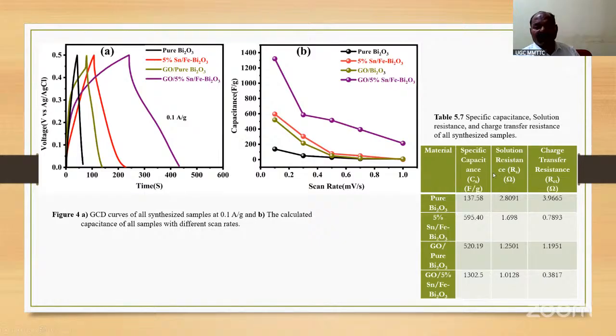For this it is 137.58 farad per gram, and the solution resistance was also calculated. The specific capacitance we got after doping, the addition and doping of this one, is 1302.5. Okay, this is this one. And the charge transfer resistance here decreased.